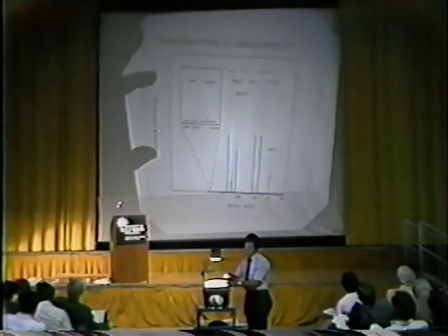We also looked for helium in the headspace. We wanted to see whether or not we could resolve helium in the presence of air. We looked on what we believe to be an identical model mass spectrometer to what was used in the University of Utah studies. We were able to see helium at its appropriate mass to charge ratio in air. Relative to argon peak, the ambient air had 4 parts per million plus or minus 1 part per million helium.